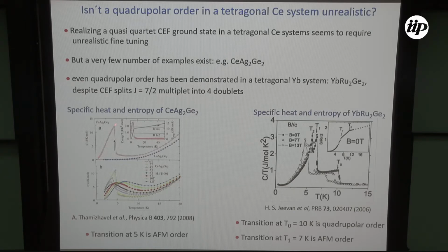Just by integrating the transition, they obtain the entropy, and you see that just above the transition you have almost collected R ln 4. So in this case, the crystal electric field splitting is less than approximately 10 Kelvin. So it's possible. In this case, it's clear that the transition is a pure magnetic transition. There is no evidence for a quadrupolar transition.